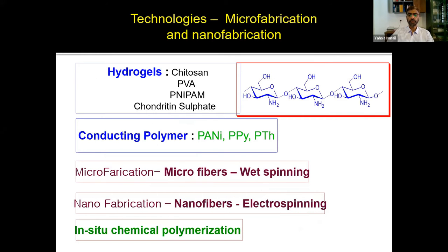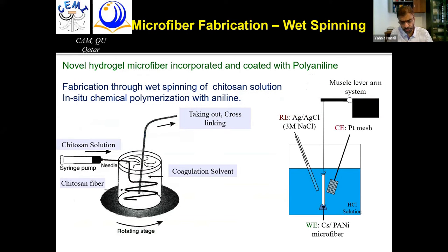So what I'm going to show is the results on polyaniline, polypyrrole, and then with chitosan and PVA. The first technology that we employed is microfiber fabrication through the wet spinning method. It's a very simple method. You can prepare a solution of a hydrogel using a syringe pump. You have to find a suitable coagulating medium, and you have to be very careful with the viscosity of the polymer solution. And then you make a coagulate in a proper coagulation medium using a suitable syringe pump with a proper radius.